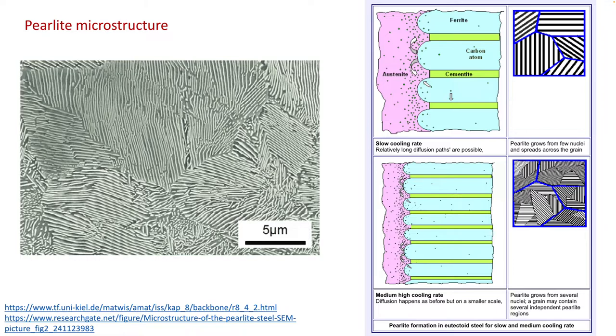Now let's look at each phase in details. Pearlite should not be a stranger to you. And you have the lath structure with the ferrite and cementite plates alternating in the microstructure. Note that not all pearlites are the same. Again, depends on the cooling rate. You can get coarse pearlite when the cooling rate is low, and fine pearlite if the cooling rate is high. If the cooling rate is low enough, in each austenite grain you can have only one colony of those pearlites. If the cooling rate is very high, then you can have multiple colonies of pearlites in one prior austenite grain.